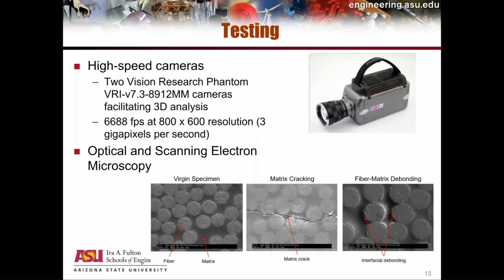And finally, we also have access to excellent optical and scanning electron microscopy that we use to find out exactly what's inside the material before it is tested, which I'm calling here as the virgin specimen, and after it is tested to show what are the different type of damage and failure that can take place inside the material. So here you can see matrix cracking, here you can see debonding between the fiber and the matrix.